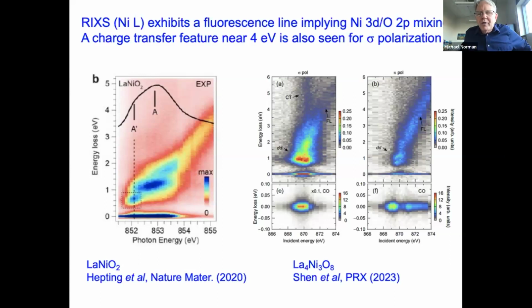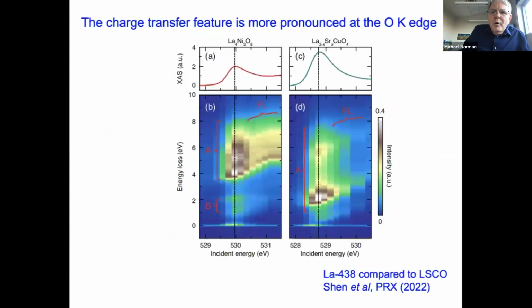So as you can see, the charge transfer gap is significantly larger in the nickelates than in the cuprates. You can obviously see this charge transfer feature much more pronounced in the oxygen K-edge. On the left, you see the 438, where the oxygen features range between 4 and 8 eV. Whereas, although the upper edge of this is pretty much the same in LSCO, the lower edge goes down to about 2 eV in LSCO. And the FL feature is, again, the fluorescence line.